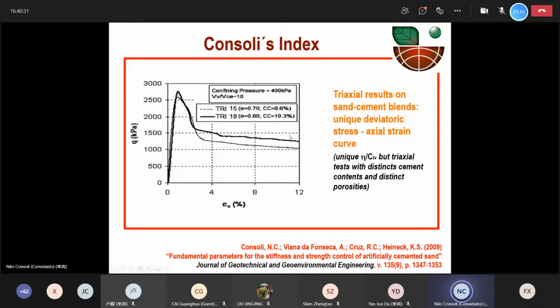This was also published in 2009 in the Journal of Geotechnical and Geoenvironmental Engineering. So we can say at this moment that besides unconfined compressive strength, splitting tensile strength and even initial shear stiffness, the whole stress-strain curve is also controlled. For example, if I have a unique value of porosity/volumetric cement content, I can have the same result even with different void ratios and different amounts of cement.